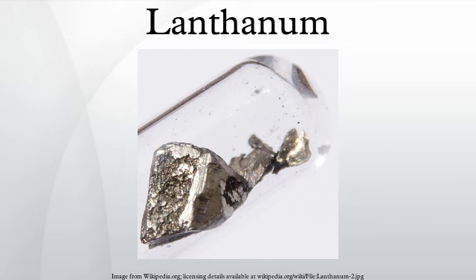Modern uses of lanthanum include: 1. The material used for the anodic material of nickel metal hydride batteries is La Ni3.6 Mn0.4 Al0.3 Co0.7. Due to the high cost to extract the other lanthanides, a mischmetal with more than 50% of lanthanum is used instead of pure lanthanum. The compound is an intermetallic component of the AB5 type.